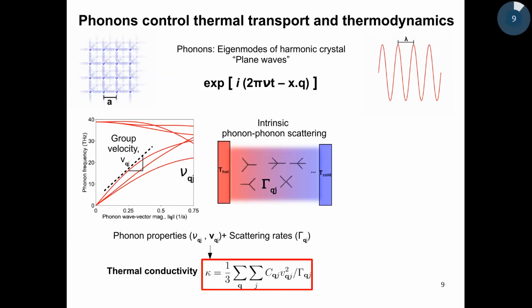So knowing these properties like phonon frequencies, group velocities, and scattering rates, you can put them together into a kinetic theory expression to calculate the thermal conductivity of any material. The expression here shows that the thermal conductivity of a material is represented as a sum over all phonon modes in the crystal, that is the sum over the wave vector and sum over the polarization J of heat capacity times velocity squared divided by the scattering rates.